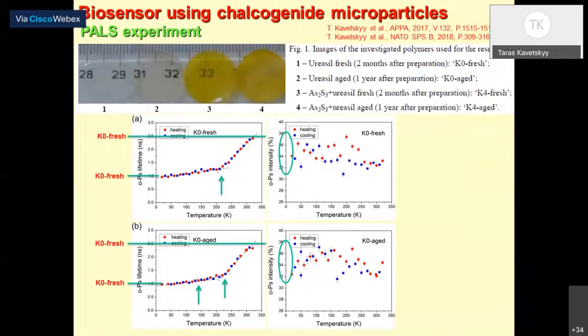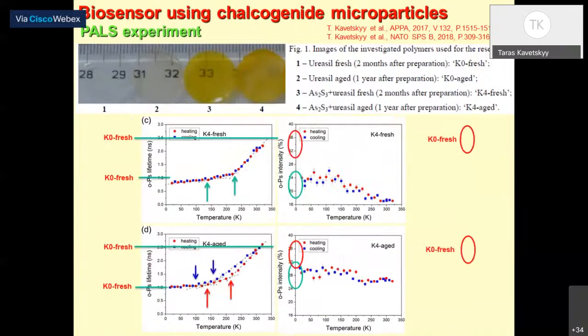Using positron annihilation spectroscopy, we studied four polymers: fresh, aged, and these with clusters, fresh and aged. We mark them K0 and K4, fresh and aged. When we compare, for the K0 fresh sample we have one Tg indicated, the glass transition temperature, but after aging we have a double Tg and a little decrease in the free volume, like a shrinkage effect. Next slide. When we compare with the resin matrix with chalcogenide clusters, K4, in the case of K4 fresh we have a double Tg, and in the case of the aged sample we also have a double Tg, but we have some hysteresis in heating and cooling. Next slide.